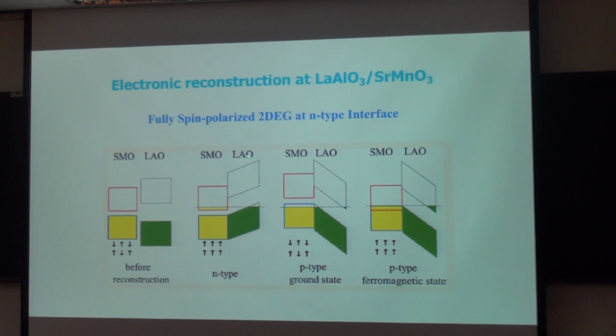The explanation is very simple. Since the formerly empty eg orbital of manganites is now partially occupied, these itinerant electrons will mediate double exchange ferromagnetic coupling between the previously localized 3d magnetic moments. So the ferromagnetic ordering develops. For the P-type, the holes reside mainly in the oxygen p state. So there's no change of the exchange interactions. So the system is still the antiferromagnetic type.